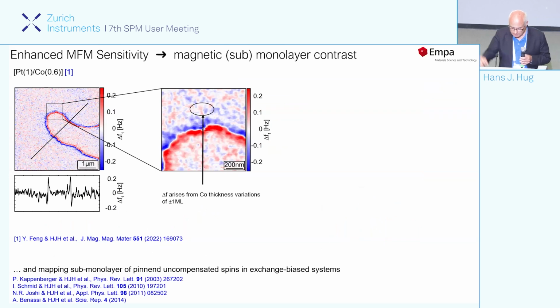Now that's an image, right? And what you see here is a 3-atom thick magnetic film. And we record a stray field of a 3-atom thick film. Actually, we can also measure monolayers as long as they have domains and generate a stray field. And you may say, yeah, but there is a lot of noise in these figures. Well, that's actually real noise. That's noise given by the sample, not by the measurement. That's because nobody in the world can fabricate a magnetic film that's perfectly 3 unit cells thick.